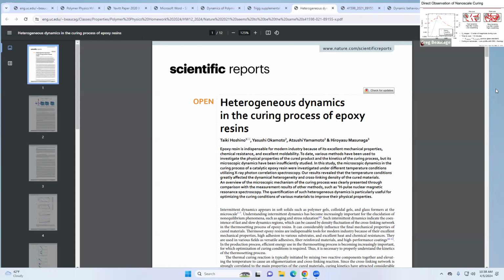And we proposed that this was a powerful technique because one way we would do this is by mechanical testing, right? Maybe rheology or DMA or something like that. But once something cures, it's really hard and stiff, right? It's hard to tell how much stiffer and harder it actually gets once it gets into that regime where it's kind of locked up as a solid. Here, we're probing at the nanoscale, right? Much finer, smaller detailed behavior. And what we could see is that that curing reaction progressed much deeper, thousands of seconds into that process, whereas in rheology, we would have just seen it plateau and just hold out, right? So there's still something going on at that nanoscale about the cross-linking and the curing reaction that we can actually measure with this technique.